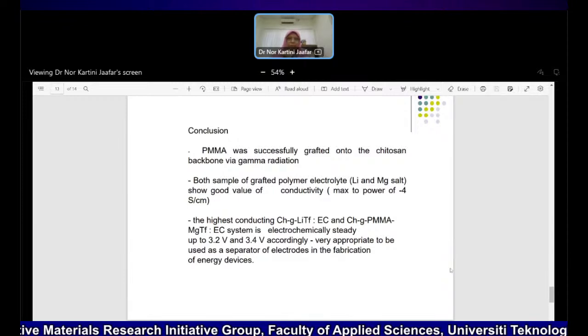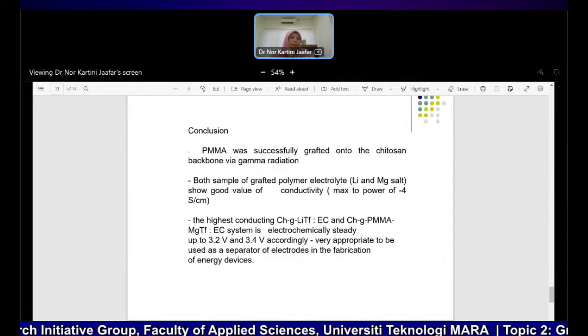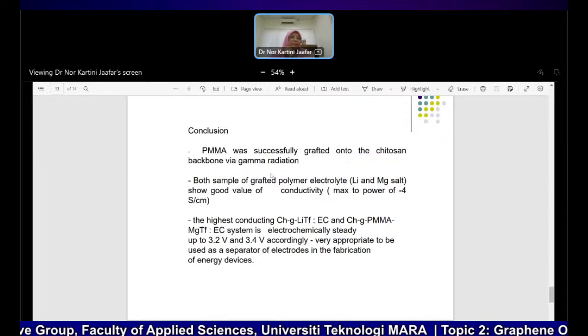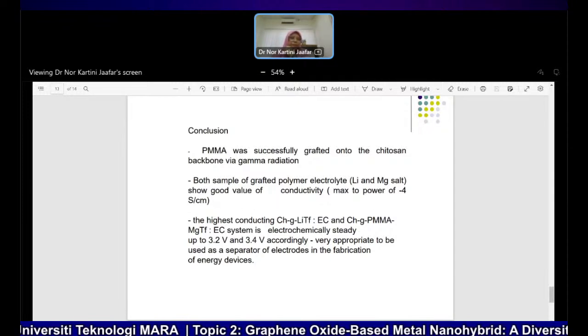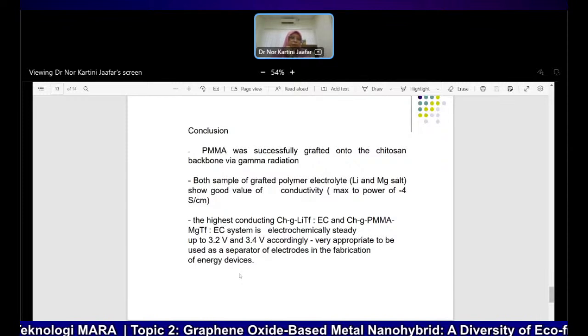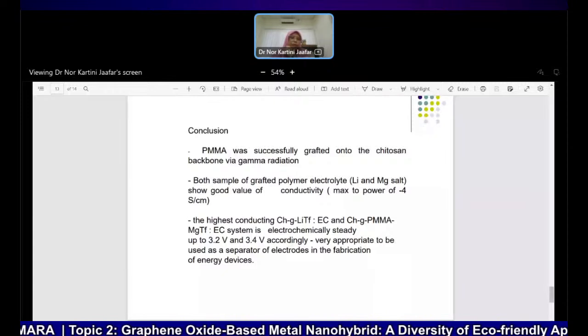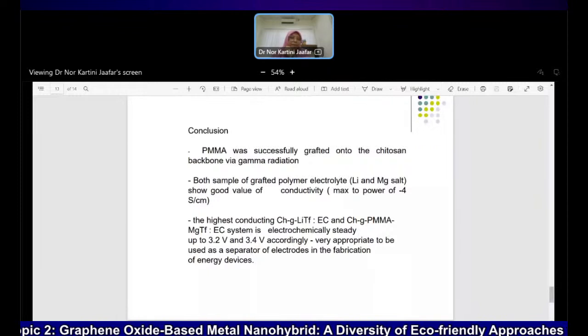So, conclusion from my study: PMMA was successfully grafted onto the chitosan backbone via the gamma radiation method. Both samples of grafted polymer electrolyte, lithium and magnesium system, show a good value of conductivity, maximum up to power of -4 Siemens per centimeter. Both systems also show very good electrochemical stability of potential difference up to 3.2 volt and 3.4 volt accordingly. So it's very appropriate to be used as a separator or electrode in the fabrication of energy devices.